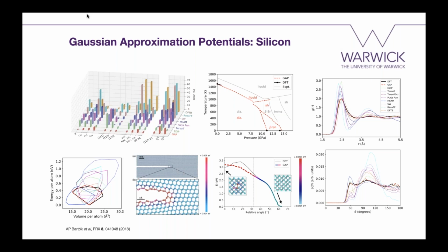Further to the left, there is a crack tip simulation, again color-coded by predicted errors. The good thing is that this is a realistic crack, so it's basically the same that some of us found in DFT quite a few years before. So the surface reconstruction and the way the crack tip propagates is completely realistic.